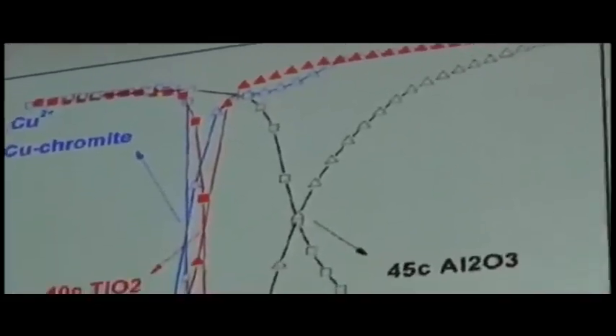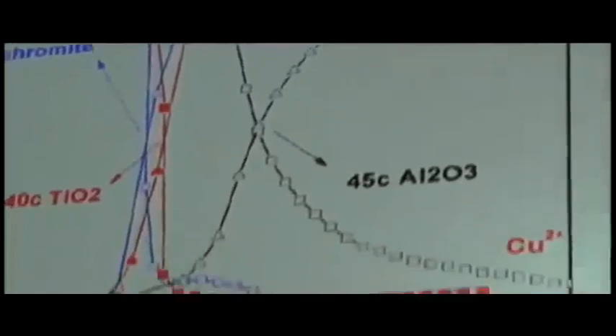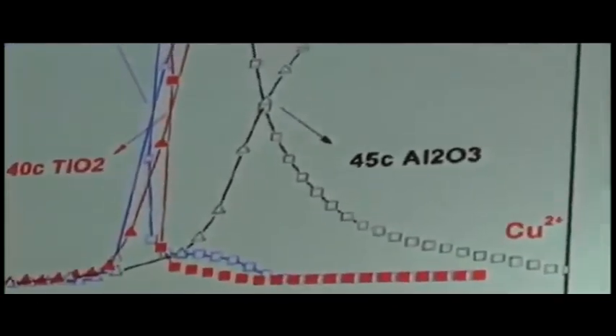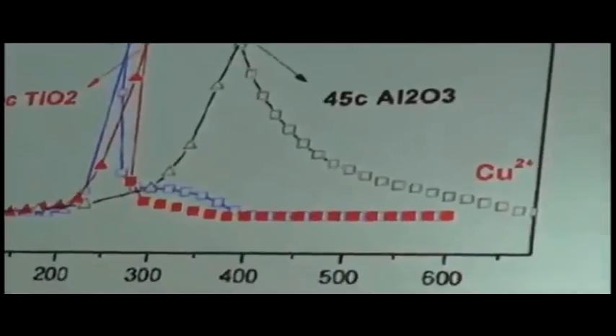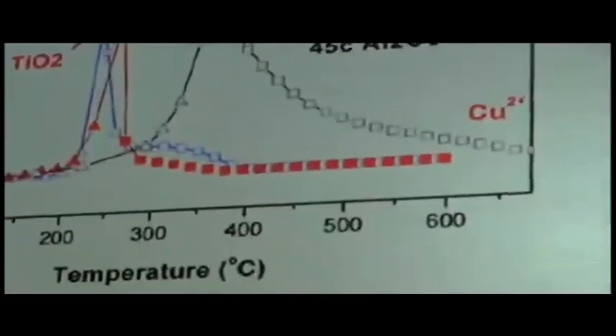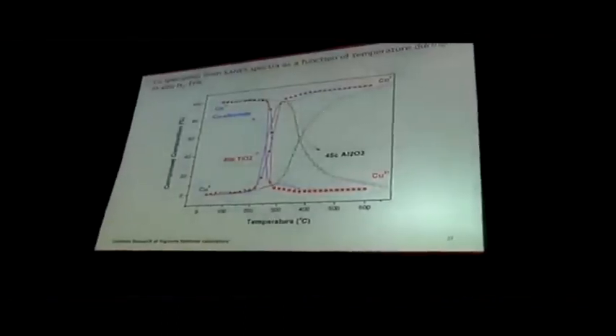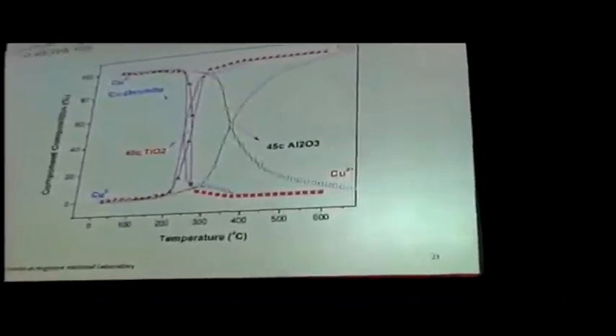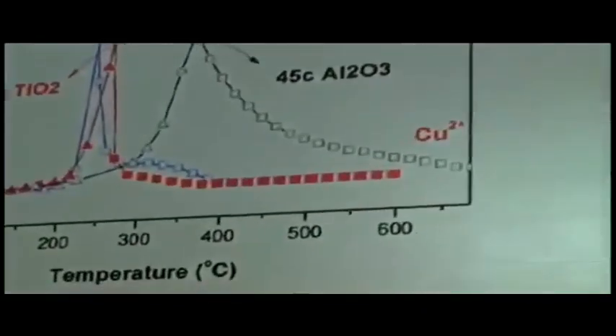So if you look at now comparing that to the red curve, which is 40 cycles of TiO2, you can see that those curves lie almost on top of each other. So the reduction potential for the copper material with the titanium overcoating is remaining exactly the same. So we haven't lost the effective copper material that we're gaining here. We're just gaining some stability from that. The converse of that, of course, is the black curve, which is the aluminum oxide overcoated material. And you can see that that reduces at a far higher temperature, which is what we had seen in the standard TPR. But this actually shows us exactly what's going on with those particular metals there.